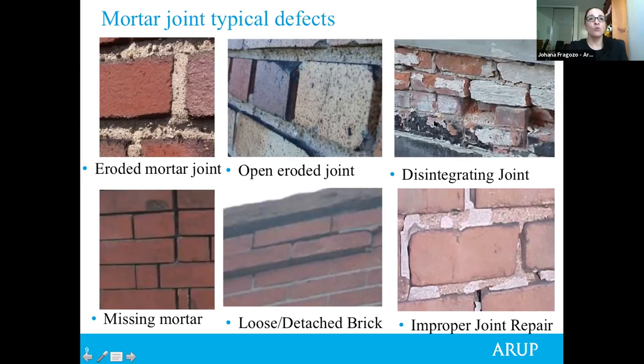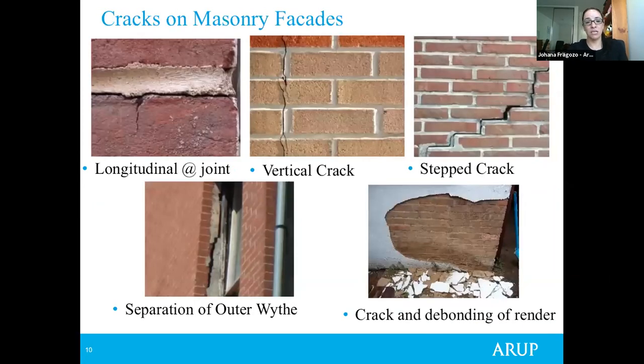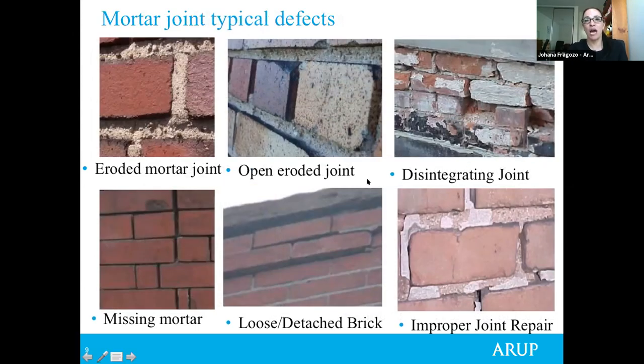Then the disintegration of the joint, which could be caused by dissolving of constituents, especially lime in water. This is particularly a problem in areas where water is trapped or where there is sulfate attack, which is not very common in the Australian environment where commercial buildings are located. In this case, the mortar loses its binding function and the brick is practically being held by gravity forces and friction, which is quite highly dependent on the level of humidity and the weight of the elements above the wall.